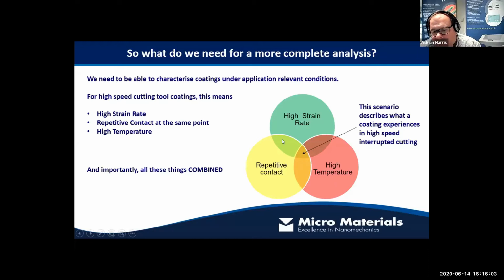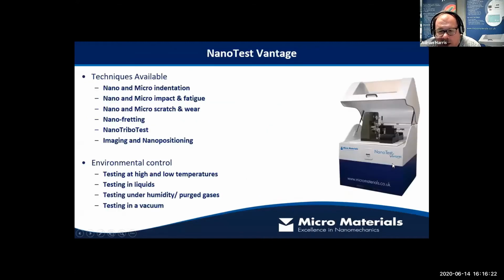So if we put these things together on this little Venn diagram here, we've got this region in the middle. And this region in the middle is this combination of high strain rate, high temperature, repetitive contact. And that describes pretty accurately what a cutting tool experiences. So we need to be able to perform tests in this region if we can. How do we do it?